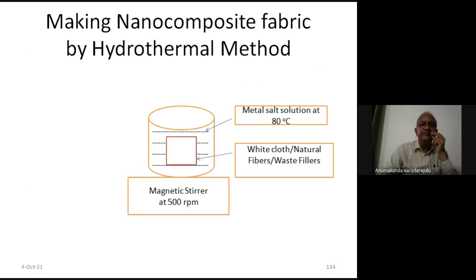How did we do it? This is a one single step method. You don't require any external chemicals. So this is the metal salt solution at 80 degrees. You require a magnetic stirrer with a heater, and the heater is maintained at 80 degrees. And then we dip directly the cloth, white cloth or natural fibers or any material. So if you want to convert that into a nanocomposite, just dip them and then allow it for 24 hours.